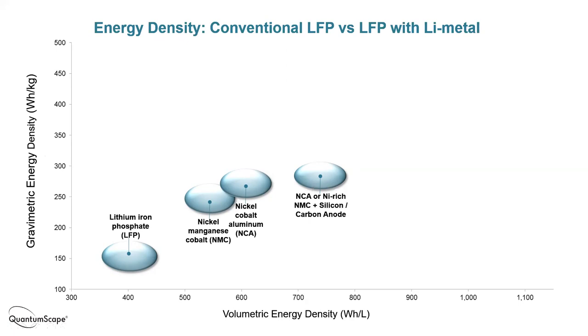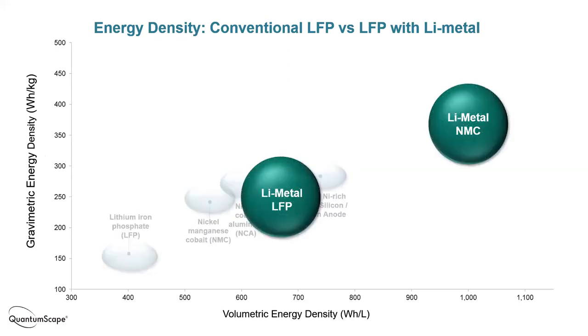So now again, if you take these particular cathodes requiring no major modifications, and use the solid state lithium metal approach, this is what you can see. So the low cost, long life LFP system can come up to the range of those other higher energy materials. And if you really want to go for the maximum energy density, the lithium metal NMC system is about 1,000 watt hours per liter. So that's a 50% improvement over today's state of the art.